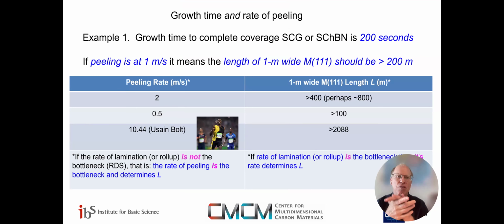So let's consider growth time and rate of peeling. So let's say we've got a setup that we can grow well on, whether it be liquid metal or M111 surfaces, and we're going to grow our single crystal, but it takes 200 seconds. So if we want to peel at the rate that Usain Bolt runs at, then we are going to have a several kilometer long growth section that we then run around and peel all of it, or it moves in some manner past the point where we're peeling.